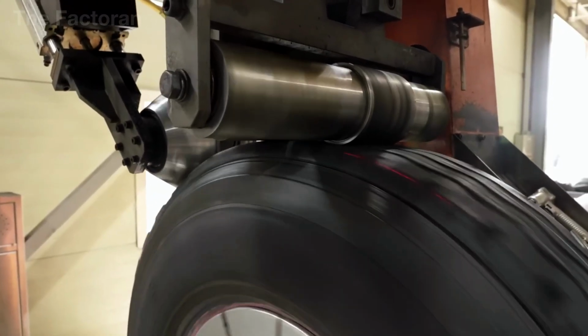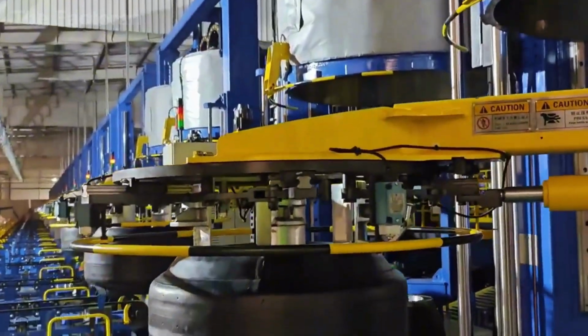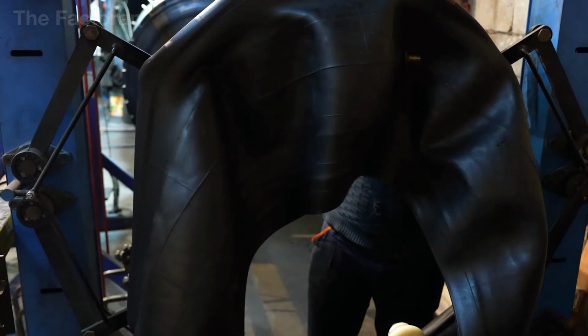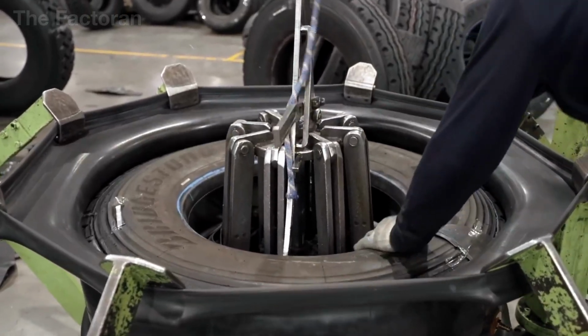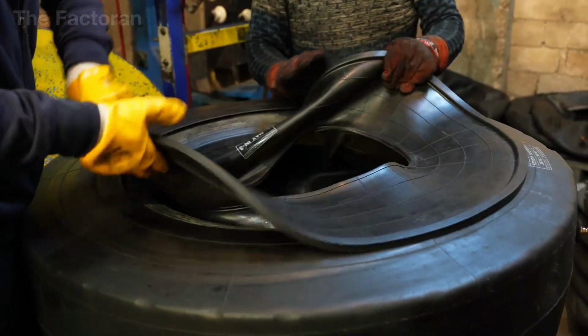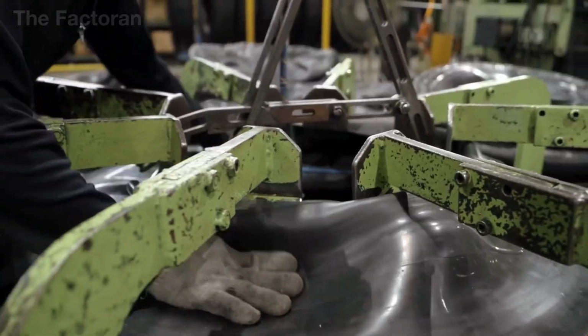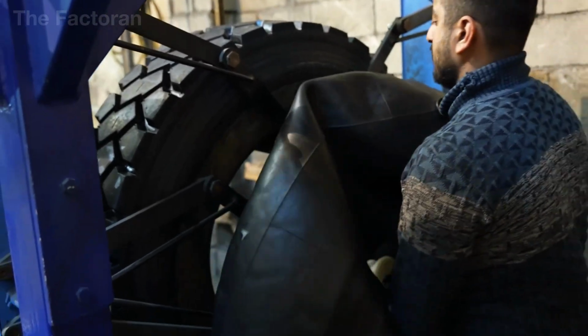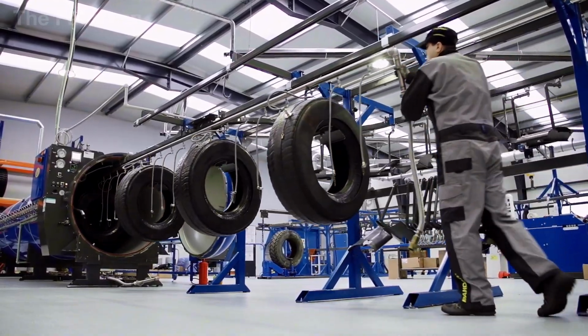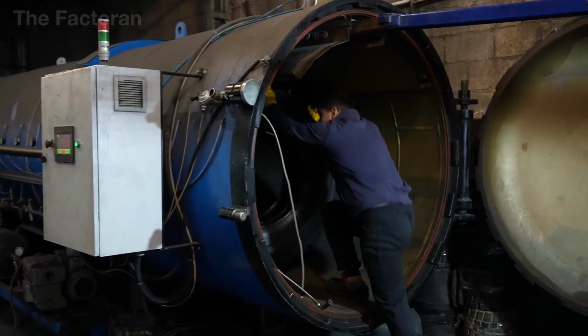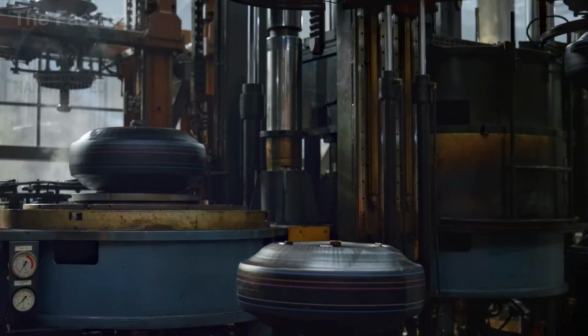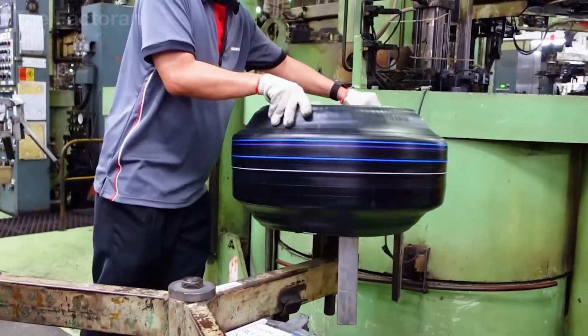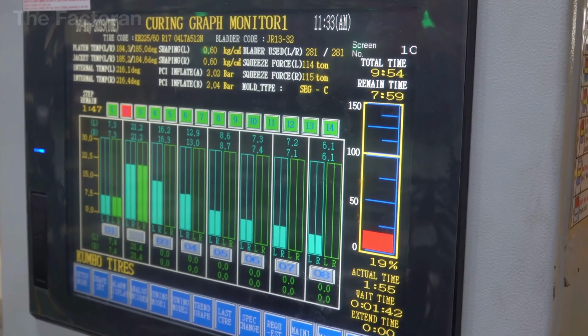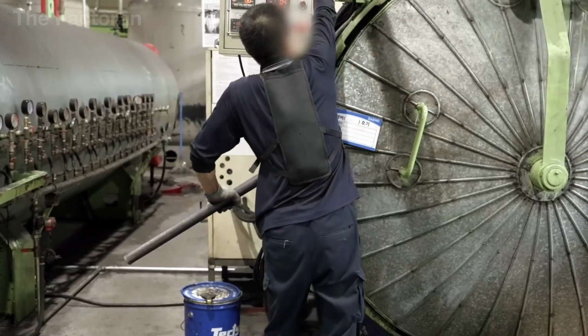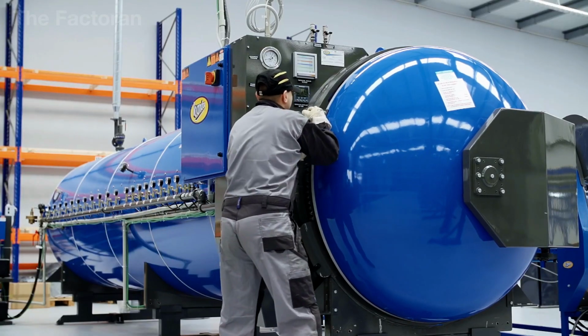At the final stage, the tire enters the vulcanization process, the cooking phase of the entire procedure. Before being placed into the heating chamber, an enveloping step is carried out. The entire tire is wrapped in a special rubber membrane combined with a sealed airbag. This outer layer acts like an armor, helping to distribute pressure evenly around the surface and preventing air from seeping in during vulcanization. When the tire is placed into the curing chamber, the temperature can reach over 200 degrees Celsius, while the high compression forces the new tread to bond firmly with the old casing. The heat causes the polymer chains within the rubber to rearrange, forming durable cross links that both increase hardness and maintain elasticity. After several hours, the result is a rejuvenated tire with sharp tread patterns, almost indistinguishable from a brand